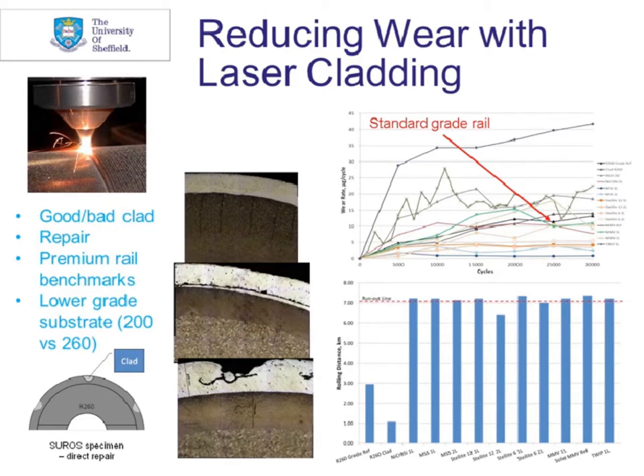In the graphs on the right hand side, you can see roughly where standard grade rail fits in the wear graph at the top. There were some clad layers that gave a worse performance, but there were some that gave a very much better performance under the conditions we tested at. And it's those materials we've gone forward with in our subsequent research.